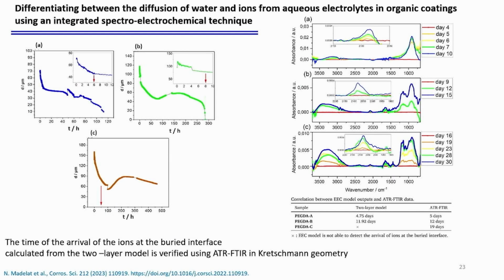To prove that, we again made the coatings. We put them on the PVD-coated crystals, and we looked at the resistivity profile as a function of time compared to the infrared measurements. And we could prove that our impedance measurements could indeed predict the ion transport, because there was a correspondence between the arrival of the ions that we were measuring with the infrared data and these impedance measurements calculated by the resistivity profile.